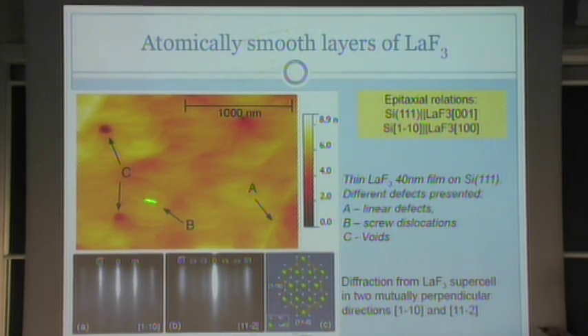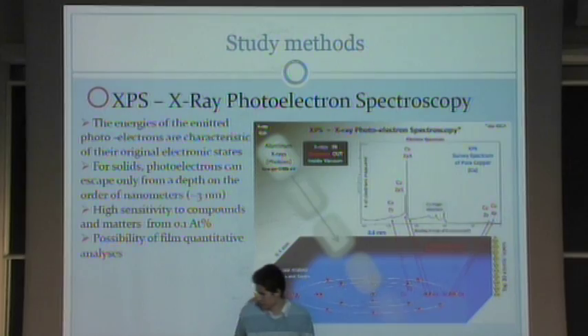And of course, there were several defects such as voids, screw defects, or linear defects. But we've already understood how lanthanum fluoride grows on silicon and the crystal structure of the lattice of lanthanum fluoride on top of silicon, which is quite useful for future studies of these layers. To understand the chemical composition of the layer,